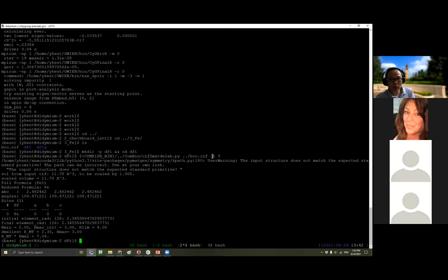And this inline command dash K simply sets up the kinetic energy cutoff for the plane wave, which is used to expand your wave function. And in Wien2k, there are similar criteria called muffin radius times this Kmax. And here we print a similar quantity. It's roughly about 7. It's roughly about the value also recommended in Wien2k.